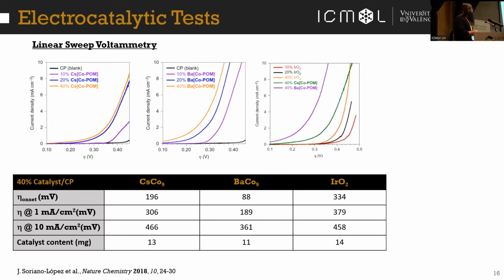And we can see that even for 40% of iridium oxide inside the blend, this cannot match the activity of the polyoxometalates. So we were pretty happy, but not happy enough, because these polyoxometalates, under certain conditions, can leach cobalt into the solution. And this cobalt, as I said before, if you leach metals under oxidative conditions, you can form an oxide. So we could be forming cobalt oxide, and it could be the active species under this condition.